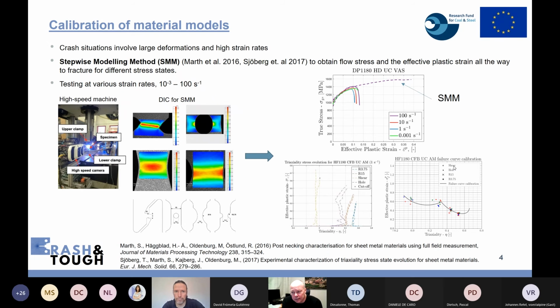So, first of all, as I said, crash situations involve both very large deformation, of course, but also quite high strain rates. So it's quite obvious we need some kind of testing in a range of strain rates, from static to the order of hundreds. So therefore, we have used the high-speed tensile test machine here at LTU. And we have also applied the method developed during the last years. It's called the stepwise modeling method. And it's a quite quick method to get the flow stress behavior from initial yielding, beyond necking, and all the way to failure. So you don't have to extrapolate any data. You get the entire curve, and you also get the failure strain.